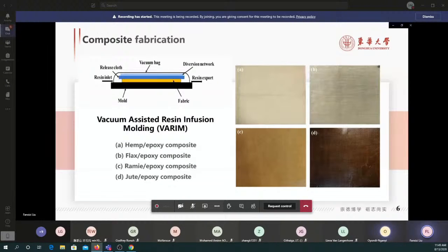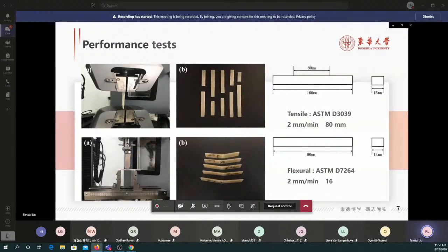In our studies, 4 types of epoxy resin composites reinforced with fabrics of hemp, flax, ramie, and jute, respectively, were fabricated using vacuum-assisted resin infusion molding, VARIM. The tensile properties of the composites were tested using a universal testing machine according to the ASTM D3039 standard. The flexural properties were tested on the same machine according to ASTM D7264.